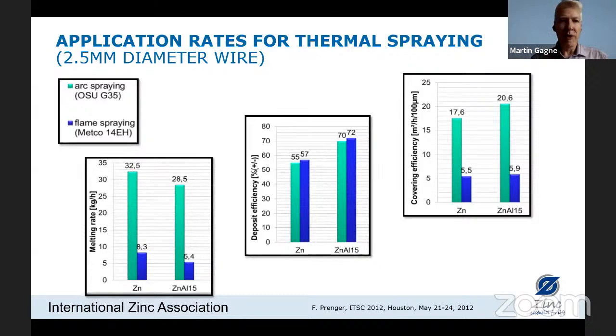Now, if we look at the difference between the two application types, arc spraying, and all of these graphs will be represented in a light green and flame spraying in a dark blue. And we'll also look at the impact of the alloy, the pure zinc and the zinc 15% aluminum. If we start at the bottom left-hand side, we look at the melting rate. So we can see, independent of the alloy, arc spraying has a higher melting rate than flame spraying. First of all, we have two wires used in the process instead of one. We can get much higher heat inputs with the electric arc than with the flame. So we can melt more kilograms per hour with arc spraying than with flame spraying.